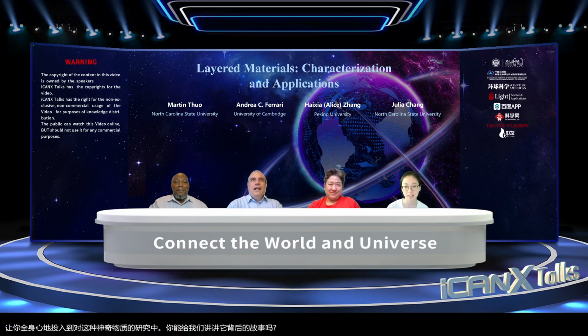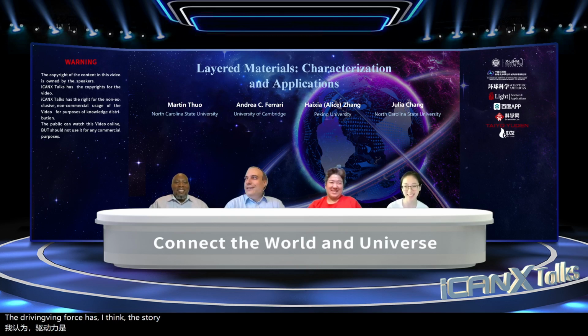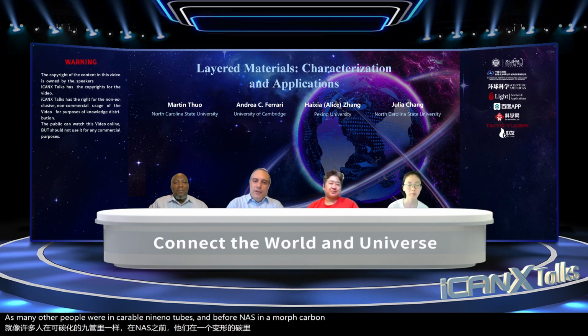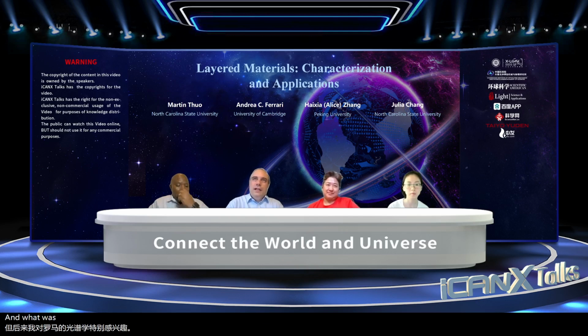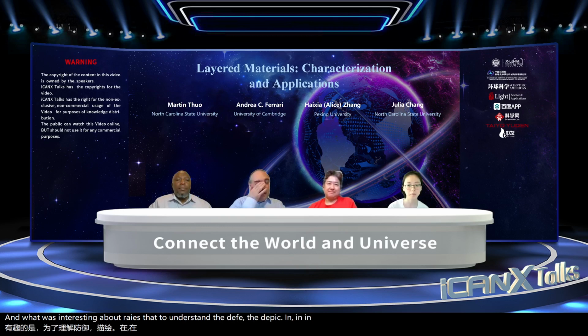The driving force. I think the story is very simple. I was working, as many other people were, in carbon nanotubes, and before nanotubes in amorphous carbon. But then I was in particular interested in Raman spectroscopy. And what was interesting about Raman is that to understand the defect, the D peak in any carbon materials, it turns out that the D peak is related to the edge of the Brillouin zone, that is the point where the Dirac cone is existing.